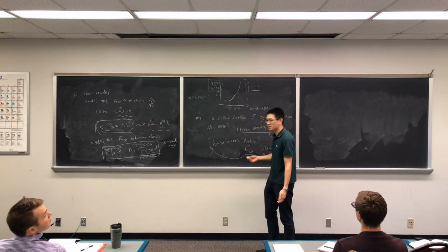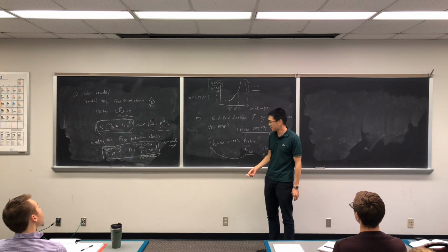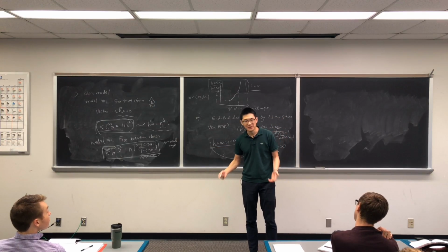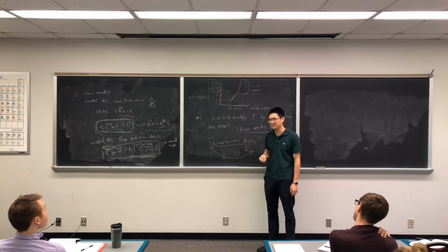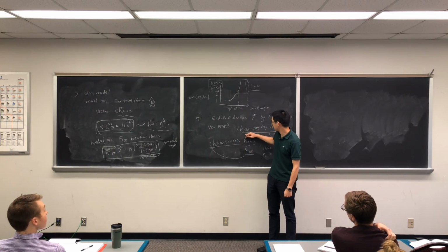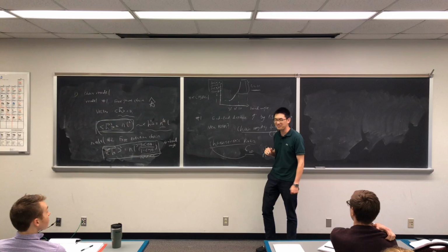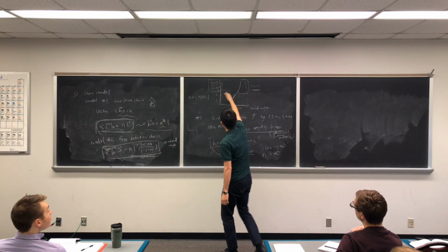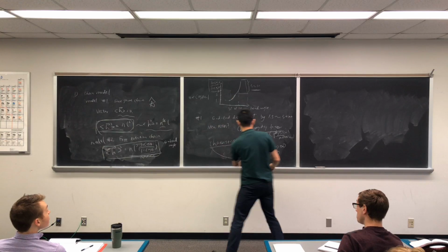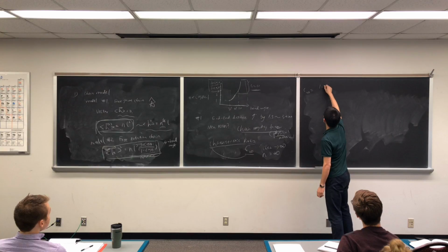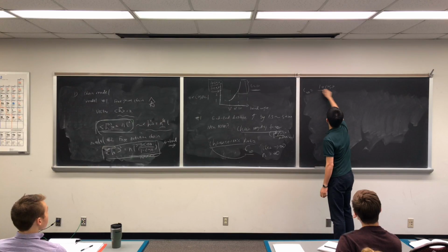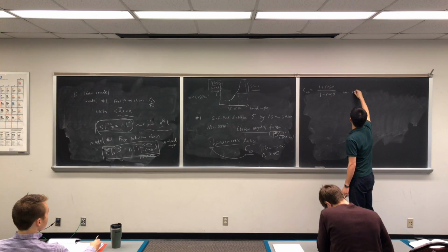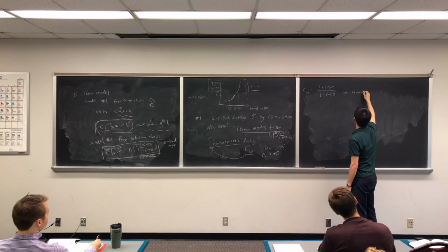But if you just throw it to any student and ask what they would understand, what is characteristic ratio? There's no physical meaning encoded into this naming, right? If I would do it, I would call it chain rigidity factor. Please? And that refers to the y-axis of the... Right, yeah. So let me write down. C infinity actually will be equal to 1 plus cosine theta over 1 minus cosine theta, when the chain is close to infinitely long.